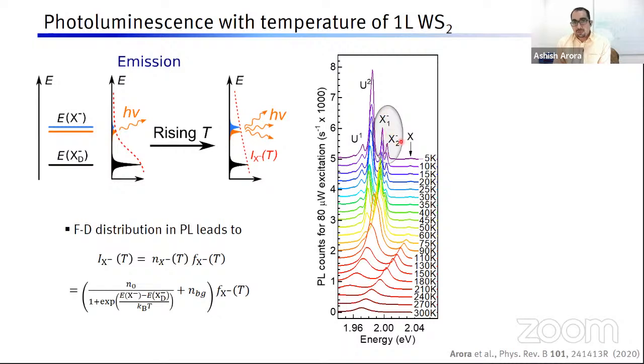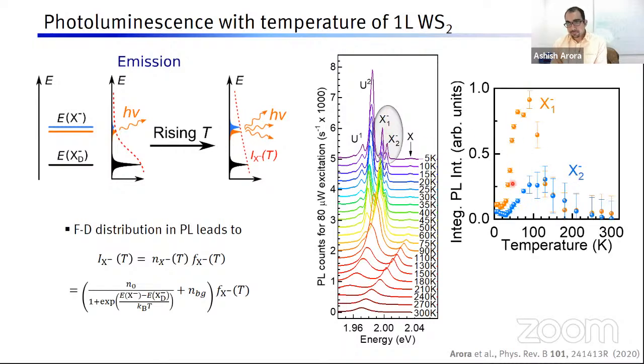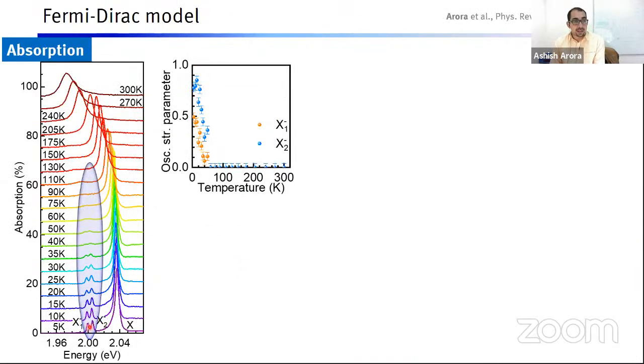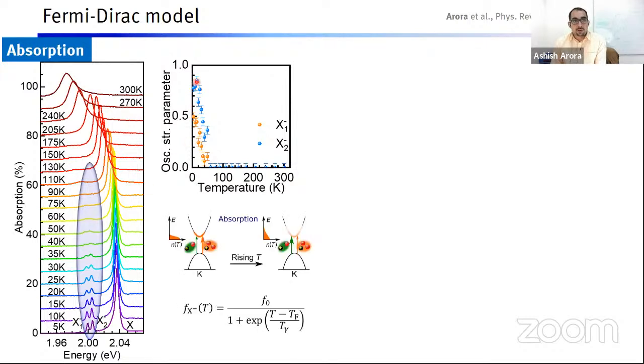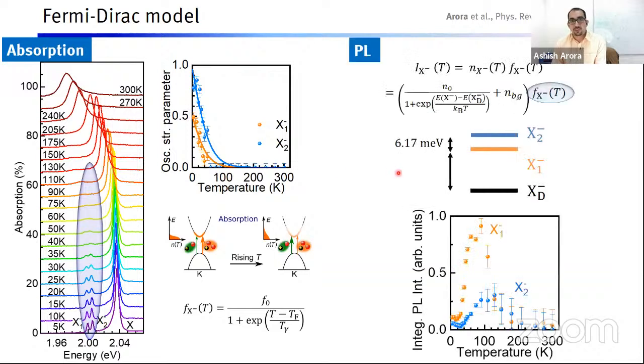These are the only trions on which we are focusing. We are not focusing on the other features. So let's plot the integrated intensities. We find that the intensity first increases and then decreases for both of these trions. We had expected the intensity to increase, but why does it decrease? Well, there is this other term, the oscillator strength, which we already measured in the absorption spectrum, which I showed you in the previous part of the talk. This oscillator strength goes down very fast as a function of temperature.